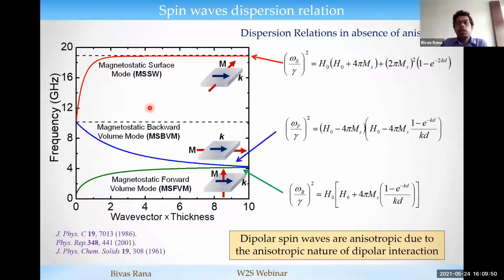Okay. First of all, the first criterion is if you know the magnetic parameters, such as anisotropy or magnetization of the system, you can calculate from the dispersion relation by yourself, and then you can identify. And apart from this, there is also a possibility to identify if you use a relatively thicker film, let's say 20 nanometer, and you are studying the magnetostatic surface mode using an antenna, because this is a surface mode. Okay, it can propagate to the top surface or the bottom surface.